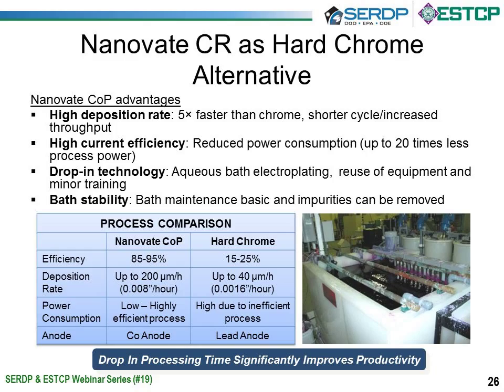It's also very high current efficiency compared to chrome. It's almost over 90% efficient, whereas chrome is only about 20% efficient. Therefore, you get 20 times less process power used in the process. It's also a drop-in technology. Since it is an electroplating process, you can potentially reuse the equipment with minimal training to the staff to use it. And the bath stability is very good.